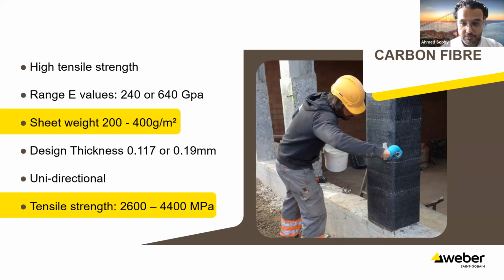I think it's quite important for us to note here that these values for tensile strength are basically for the fibers. They're not for the finished product. So when the fiber is combined with the resin, these numbers actually reduce dramatically. That's number one. Number two, even when we consider the tensile strength of the finished product, the laminate or the wrapping, we don't really take the whole amount of the tensile strength in our design and our consideration.